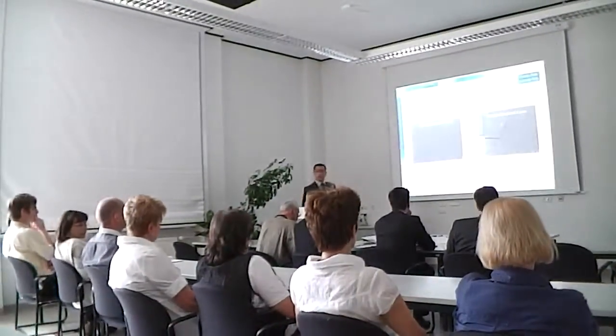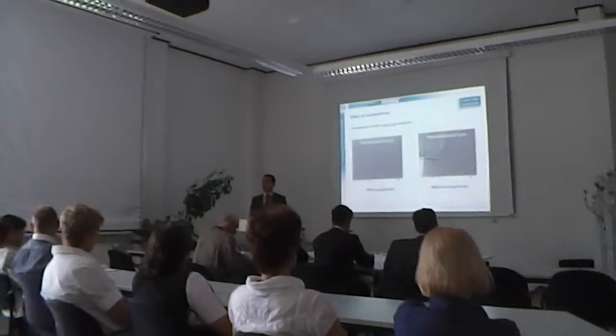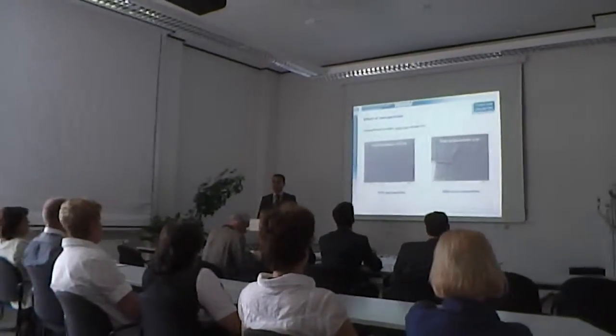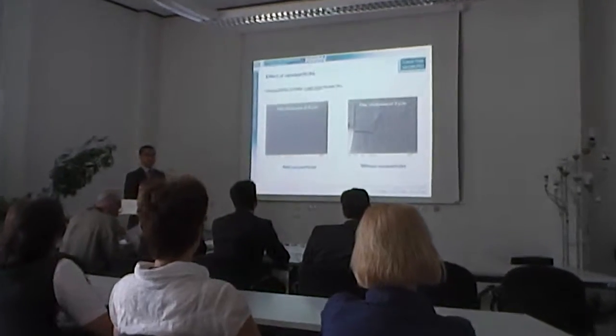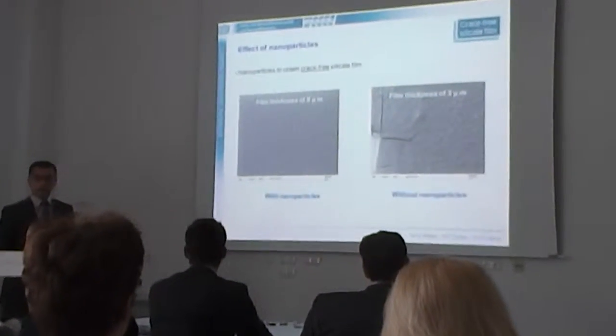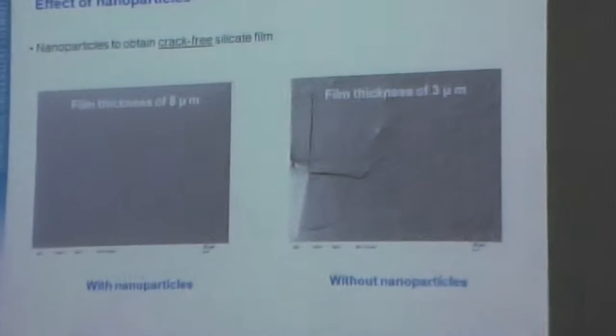The second advantage of the nanoparticles is the crack-free film. This is in the case of film without nanoparticles, that's the cracks. And in the case of film with nanoparticles, no cracks can be detected by scanning electron microscope, which can be explained that the nanoparticles reduce shrinkage in the film and internal stress in the film, so therefore less cracks.